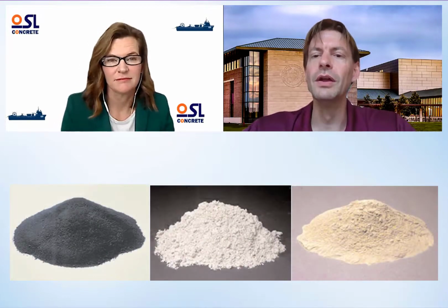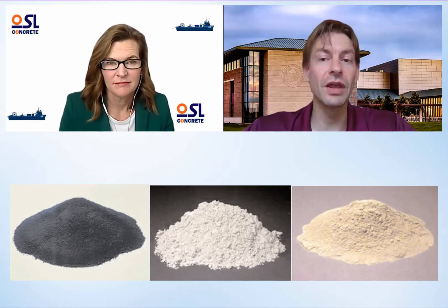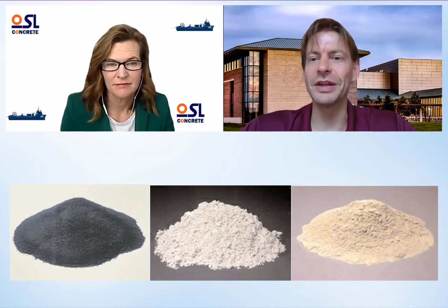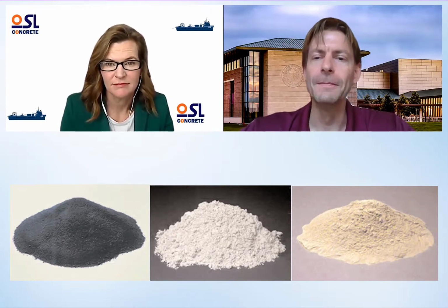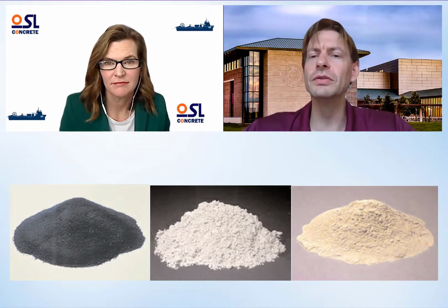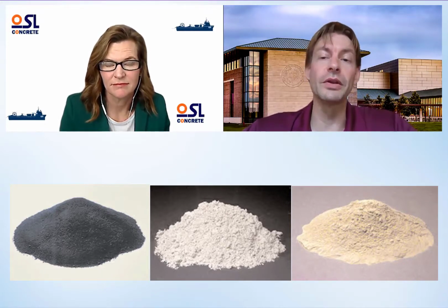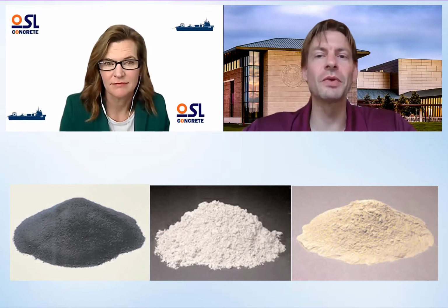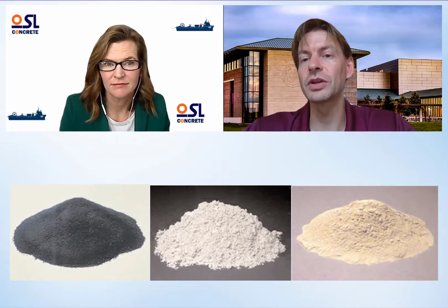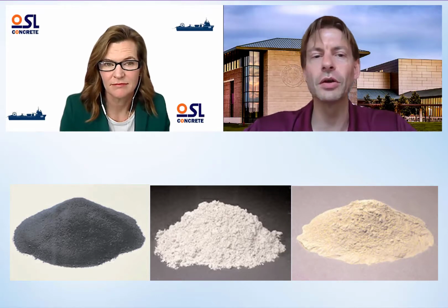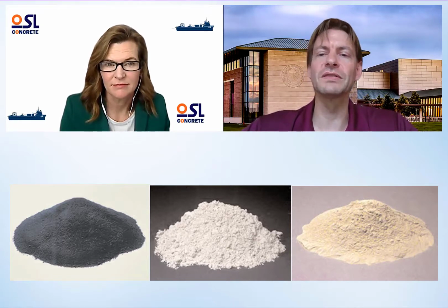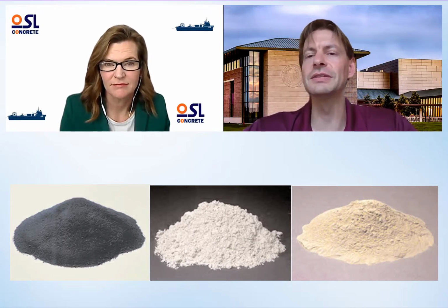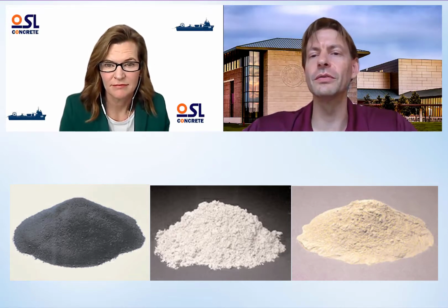So this is one of the few cases in engineering where you can have your cake and eat it too. Usually there's trade-offs in engineering. In this case, you can actually improve your concrete while reducing your cement content. Some of these mineral powders you can use are actually waste products from other industries, like fly ash, which is a waste product from coal burning power plants, granulated blast furnace slag, which comes from the production of iron and steel products. These allow you to replace a portion of the cement with waste products from other industries, and therefore lower the overall CO2 impact of your concrete.